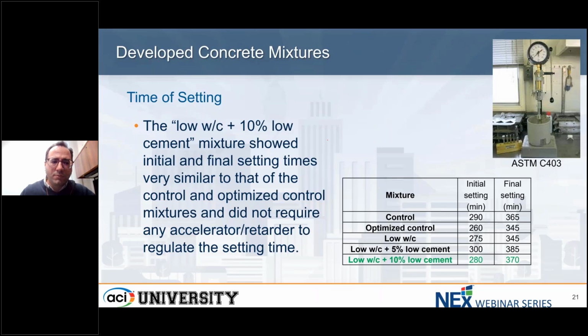The other fresh property we looked at is the time of setting. We wanted to see how this high range water reducer at high dosage impacts the time of setting. So these are the values based on ASTM C403. You see the setup here, right? You are measuring the initial setting and final setting time. If you compare the results here, the result is within plus or minus 10 to 15 minutes for the low cement or sustainable system compared to the control one. So we don't see much impact from using this high dosage admixture content.